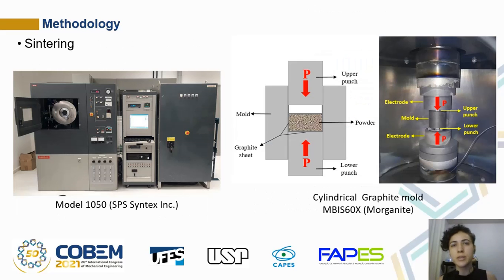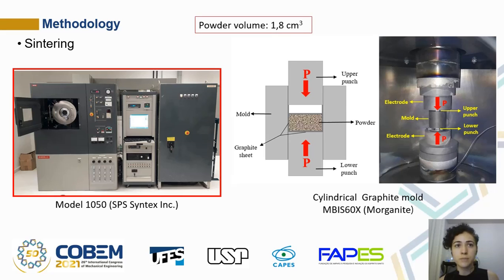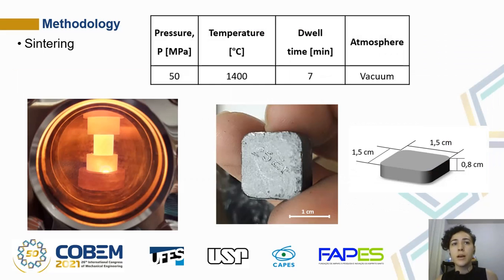The samples were sintered in a modern machine that has automatic cycle control of current, voltage, temperature, pressure, atmosphere, as well as displacement. The volume of the powders was arbitrated. The powders were manually placed into a graphite mold, and to avoid adhesion among powders, mold walls, and punch, a graphite sheet was used. The mold was placed between punches and electrodes of the machine, which promotes mechanical loading and electric discharge at the same time. A uniaxial pressure of 50 megapascal and a vacuum atmosphere of 10 pascal was applied to the powders. The dwell time at the temperature of 1400 degrees centigrade was 7 minutes.